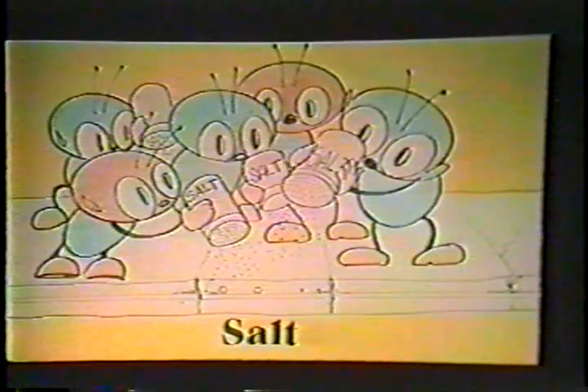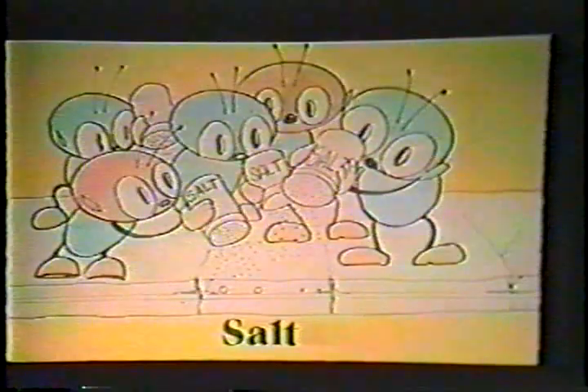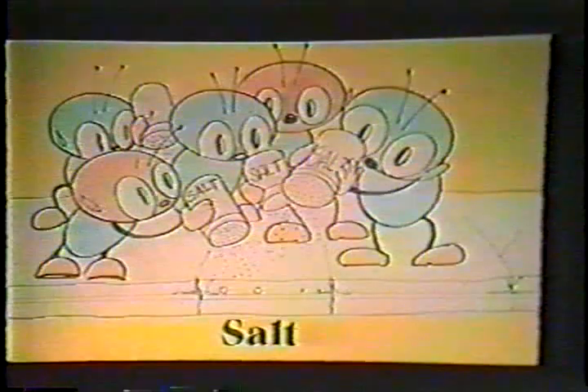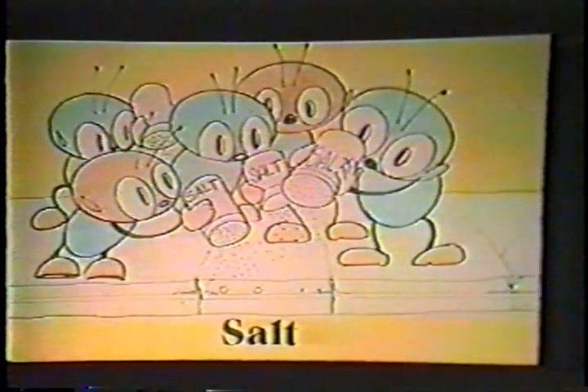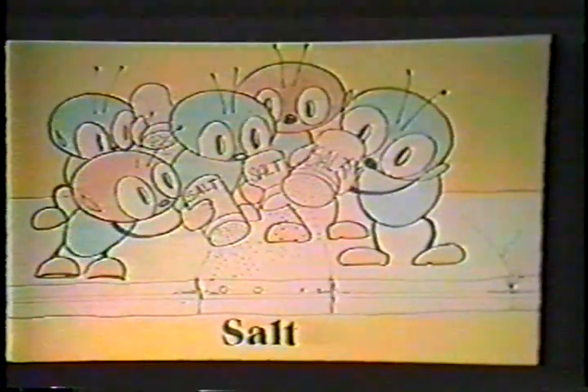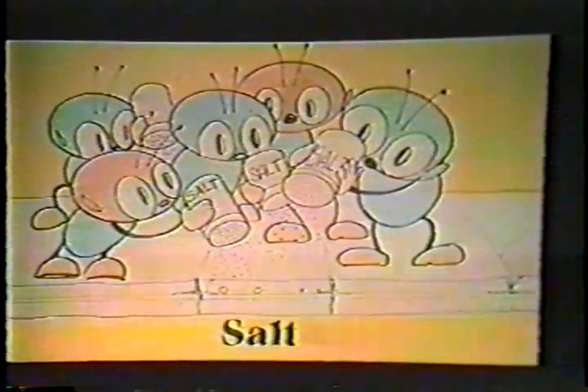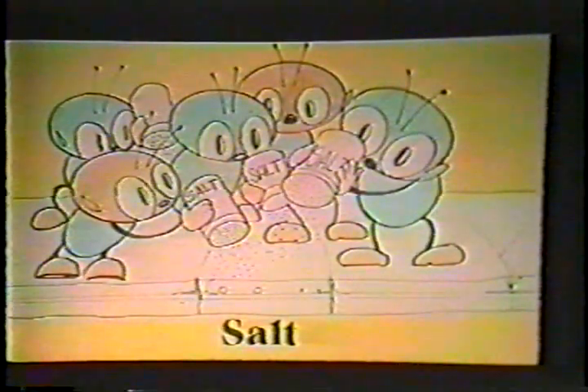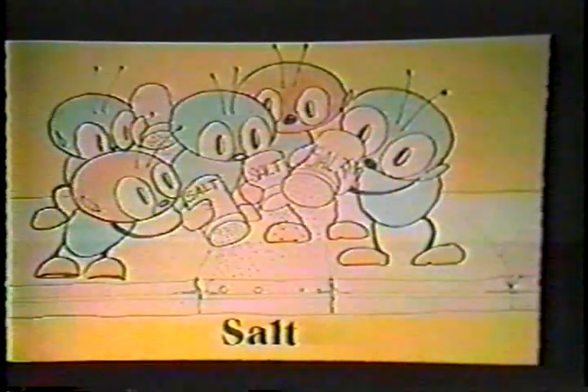The moisture bug in itself isn't that bad, but when the moisture carries salt or calcium chloride, this is real trouble. The concrete itself can tolerate chlorides, but salt and steel are two things that you certainly don't want to get together. When salt gets to the steel, you get rust. When you get rust, you can get expansive pressures that crack and spall concrete. This bug is bridge deck enemy number one. We have found that when the salt content reaches 2 pounds per cubic yard, we can be 95% certain that rusting is taking place.